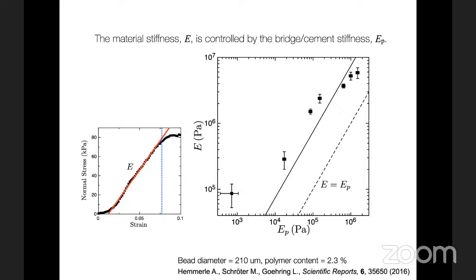And if we make that polymer stiffer or softer, we find that the Young's modulus of the cohesive assembly changes. Remember, the polymer is only a few percent in the plot here, 2 or 3% of the whole system. That polymer dominates the elasticity of the system. The polymer determines the springs between the particles, which determines the elasticity of the assembly.